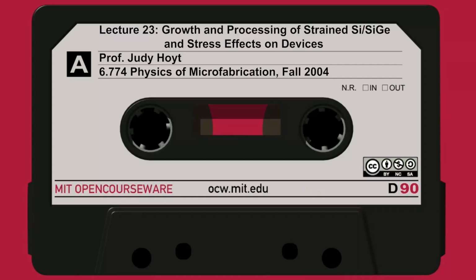And this has been verified very many times. And of course, in the MOSFET, you do see the enhanced mobility. So there doesn't seem to be any significant strain relaxation, at least when you oxidize in these type of temperatures. If you were to go up to 1,000 or more, then you could start running into trouble when the germanium starts diffusing around.